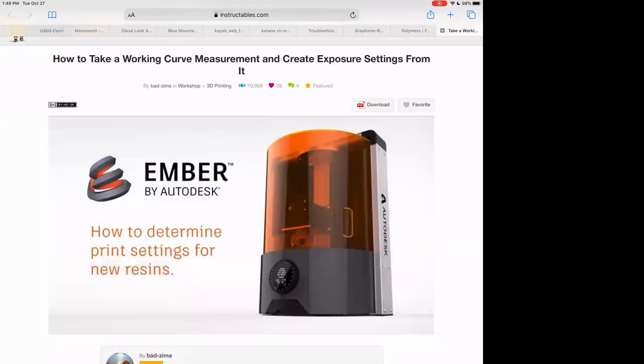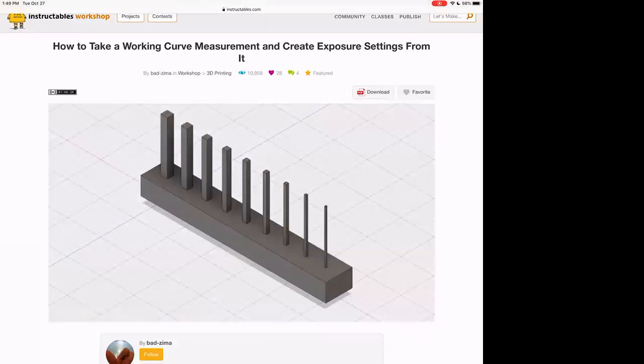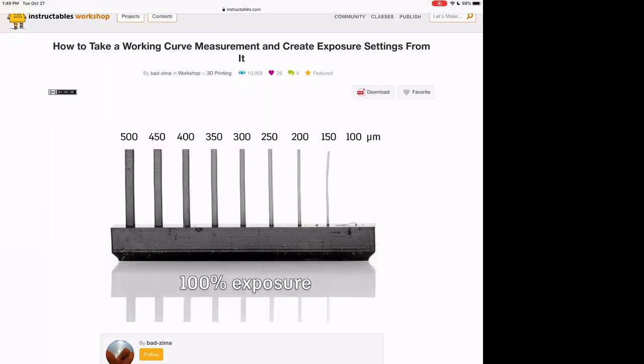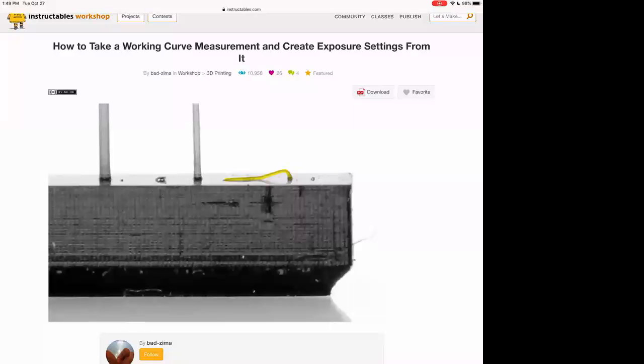It is vital to determine the precise amount of light energy, or exposure, needed to cure a 3D printable resin. Why? Let's say we have a model with small positive features. These square posts range from 500 to 100 microns in width, and they're 4 millimeters tall. Now we print it on an Ember with the proper energy exposure. All of the features turned out except for the very smallest one, the 100 micron wide post. It started to print but collapsed because it was too thin. When we print this model with only two...